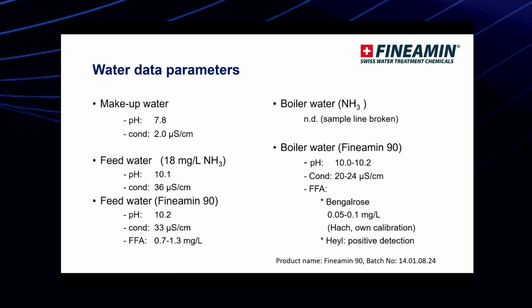Boiler water on the ammonia, we could not make the analysis because the sample line was broken. For the boiler water with Fineamin 90, the pH is between 10 to 10.2, conductivity between 20 to 24 microsiemens per centimeter, and the FFA on the boiler water is around 0.05 to 0.1 ppm. So this is using Hach and using our own calibrations.